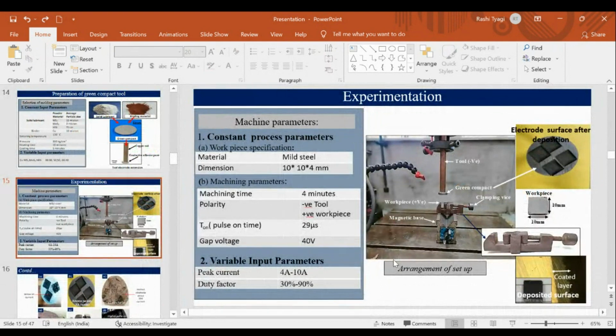So this is the experimentation work that is performed. There are the machining parameters and workpiece specification: we utilize mild steel, and for the machining parameters, 29 microsecond pulse on time and a gap voltage of 20 volts are used, and the variable input process parameters are peak current and duty factor. I have shown you the EDM process machine parameters that we can change.